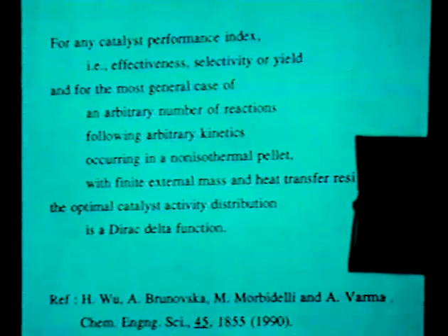There is a restriction in this which I should mention, and the restriction is that the surface area of the catalyst, typically we are thinking of noble metals, platinum, palladium, things of this sort, is proportional to the loading only as the loading is increased to a certain extent. If you go to very excessively high loadings, then you will not have this feature, and then you will have some sort of a saturation. Then it turns out that the answer becomes numerical in nature, and the answer is that it is basically sort of a distorted Dirac delta function, distorted about the location where the Dirac was supposed to have been located.